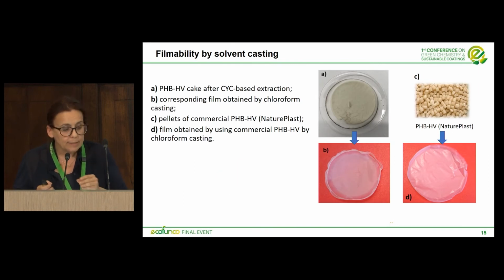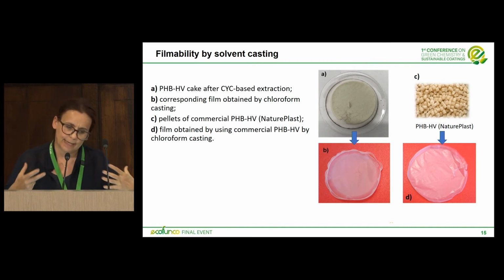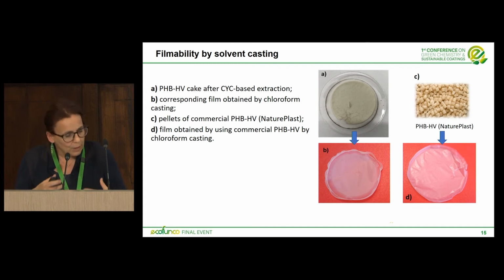So, about the filmability. The filmability of the PHB-HV extracted, due to the very small quantities of the PHB-HV extracted, was evaluated simply by solvent casting using chloroform as a solvent for the PHB-HV. In this case, you can see the films obtained by solvent casting. And the films obtained resulted with the same flexibility, opacity, and consistency.